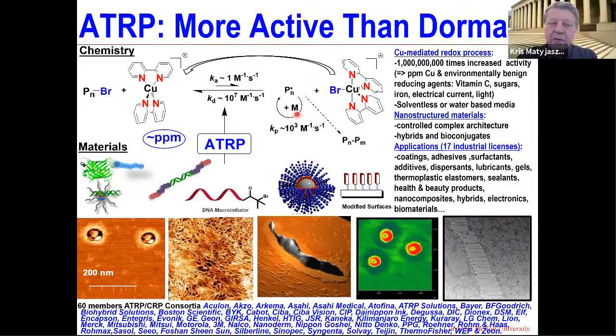So ATRP is based on a free radical as active growing intermediates. And like in a conventional radical process, the frequency of monomer addition to a chain end is, roughly speaking, around 1 millisecond. And after 1,000 monomer additions, after 1,000 milliseconds or 1 second, there is a termination process. So during this time, 1 second of the activity of a chain, it's impossible to make these beautiful structures which Craig showed, block copolymers or potentially gradient and some others. So it was a challenge for many years, how you can extend the life of a propagating chain from seconds to hours or maybe even days. And we do that by equilibrating these active species with dormant species.